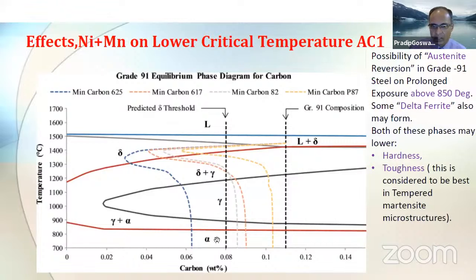These delta ferrite issues typically don't come up much in the weld metal, in the welding consumables. But when this alloy is formed into other shapes, like if they're forged or cast, then based on the pouring temperature as well as the cooling rate adopted, there are instances of some residual delta ferrite in those alloys. Definitely those have an effect on the various metallurgical properties, especially the toughness. That is why castings and forgings involving P91 are in many instances more difficult to weld than formed products like plates or pipes.